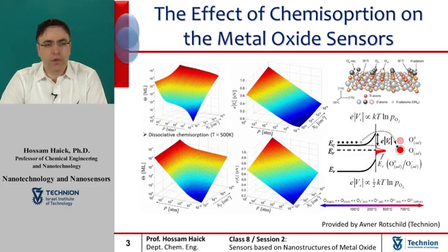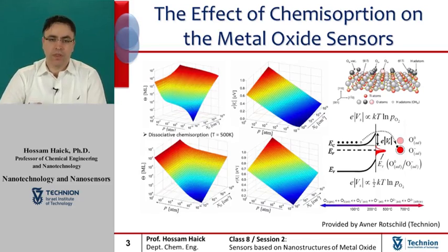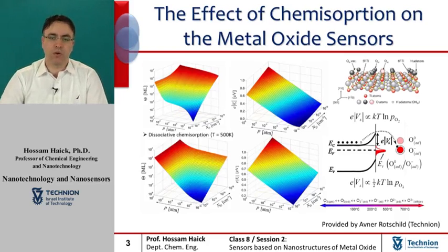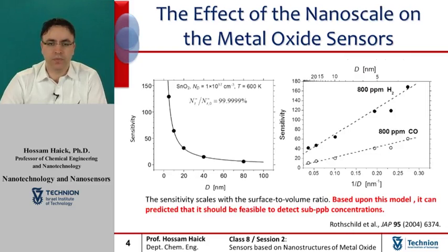However, it's important to notice at this point that due to the surface band bending, which obviously depends on the coverage of charged species, their binding energy is not constant, but is rather an implicit function of the coverage. Therefore, the conventional Langmuir model fails in this case, and you shouldn't use it when you deal with semiconductors or with semi-insulators.